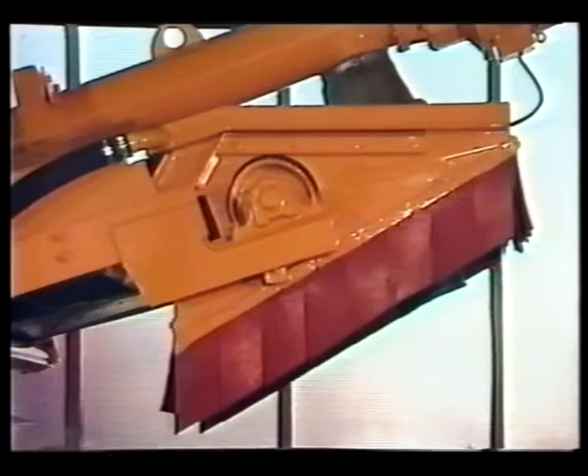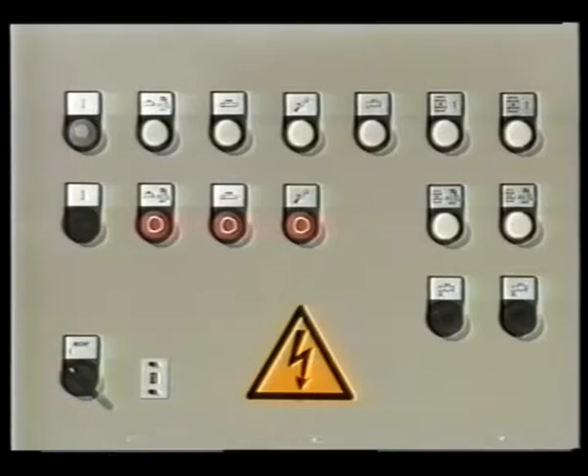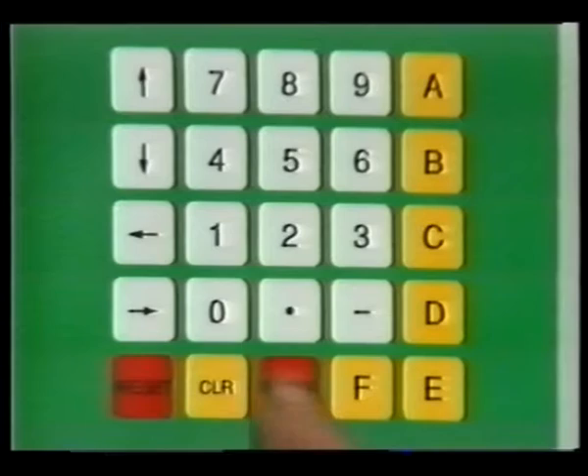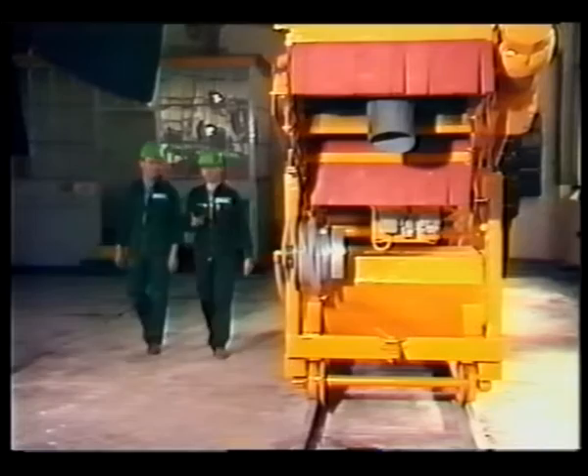The shutters can move freely over the mixing opening. The materials are injected into the mixer by means of four special nozzles. In these see-through cylinders the admixtures are pre-batched. All elements of the feeding device can be controlled from the electronic control panel, with a direct connection to the main control unit in the mixer. As an option, the amount of mixing water can also be determined by consistency measurement in the mixer. The measured values are then processed by the computer, making it possible to maintain a precise water-cement ratio even for varying amounts of water contained in the aggregates.